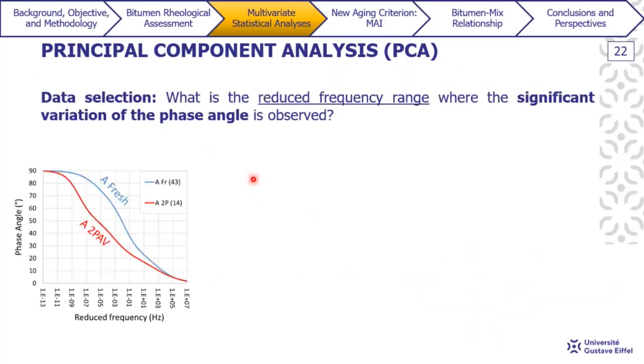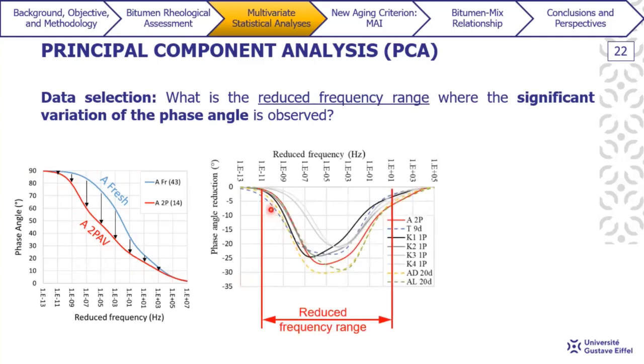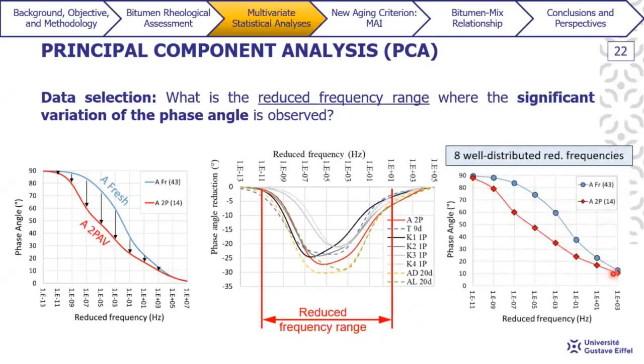So also a very important part of PCA analysis is the data selection. In this case, we had to determine what would be the reduced frequency range where the significant variation of the phase angle was observed. So for each bitumen with different aging levels, we took the freshest level and the most aged level, and we took the difference between them to determine where we could observe the most relevant variation. And then we determined this reduced frequency range here. And then to represent our curve, we set well-distributed reduced frequency values here in order to be more representative of the whole master curve.